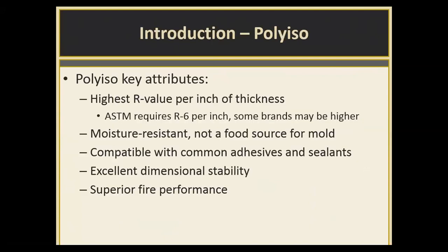Key attributes of polyiso insulation are the high R value compared to the other rigid foam boards or even the fibrous products. Fibrous products, again, using the trapped air as their means to getting R value, tend to have an R value around 4 per inch as well. So you're going to get the highest R value per inch out of polyiso. And one of the reasons why it's so readily used in the roofing environment is high R value. And the three main reasons are high R value per inch, superior fire performance, and compatibility with solvent-based adhesives, sealants, and other things you find in the building envelope assembly.